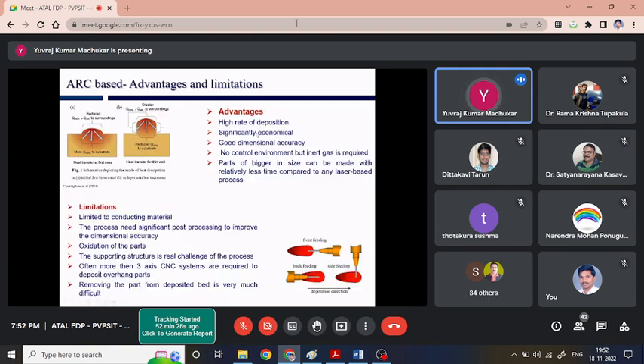Now, if we talk about the arc-based advantages and limitations, yes, of course, we have a very high rate of deposition, it is significantly economical, has good dimensional accuracy, and needs no controlled environment, but inert gas is required. Yes, of course, it is limited to conducting materials. The process needs significant post-processing to improve the dimensional accuracy. Oxidation of the part is one of the major challenges. Often a more than 3-axis workstation is required.